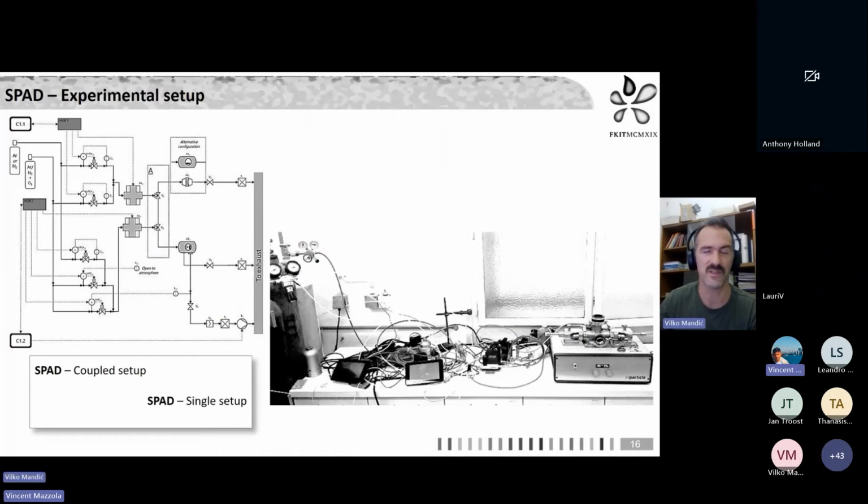It's not complete because I made a very unclear picture, but basically we have two spark plasma generators, or nanoparticle generators, and a cascade of MFCs that allows modification of the carrier gas. And why would we like to do that? Because we're not so interested in just nanoparticles of metals. We want to really go in the direction of metal oxides. So we play with the atmosphere. We make the inert atmosphere reactive.